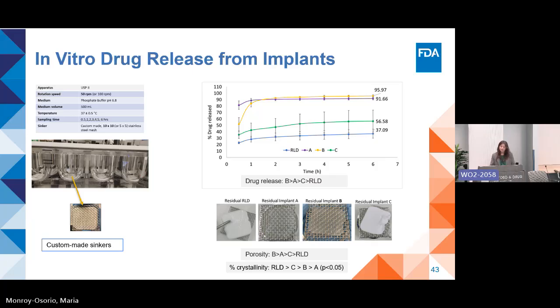release study. So the results show that for all the implants, we have observed a biphasic release pattern, where at the initial time point, higher drug was released from implant A, followed by implant B, implant C, and RLD. At the end of the 6 hours of the release study, the pattern remained the same. However, the drug release from implant B is higher compared to implant A, and then implant C and RLD drug release remained the same.